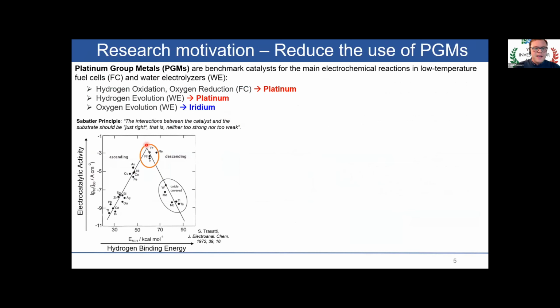Unfortunately, the most effective catalysts for all of the electrochemical reactions involved in these devices, in water electrolyzers and fuel cells, are based on platinum group metals, or noble metals, if you prefer. As you can see, the best catalyst for the reactions involved in fuel cells, the hydrogen oxidation and the oxygen reduction, is platinum, while for the reactions involved in the water electrolyzer, the hydrogen evolution, the best catalyst is platinum, and for the oxygen evolution, the best catalyst is iridium. These noble metals are located at the top of the so-called volcano plot because they have a very nice intermediate binding energy with both the oxygen and the hydrogen molecules, and so they can provide very efficient electrocatalysis.